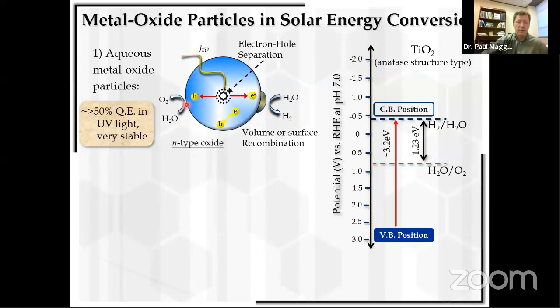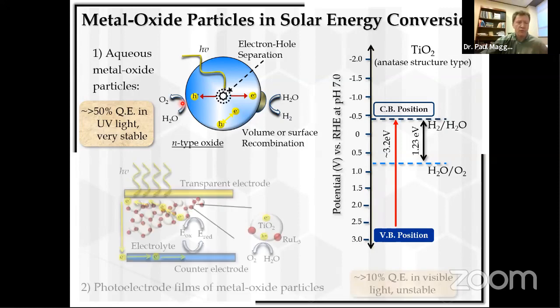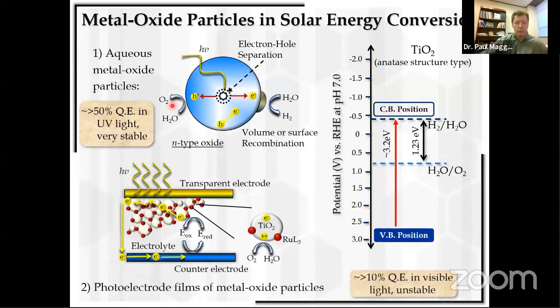In ultraviolet light, this can be very efficient in water, and groups like Domen and others have shown this, for example, for sodium tantalate, for strontium titanate. But their limitations are that they absorb only in the UV, and yet no visible light semiconductor has been found to do this efficiently. The other format that these work in is as a film.